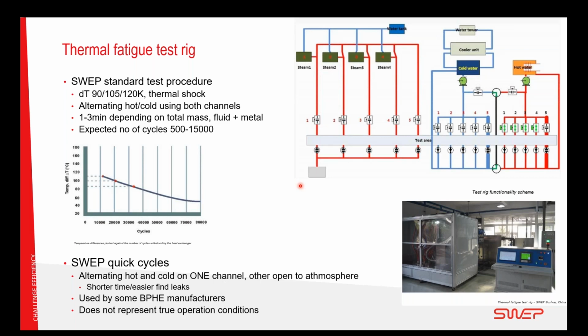And worst case, we will expect somewhere around as low as 500 cycles and then going up to 15,000 cycles. So it's very time-consuming testing, but it has been improving now, the test rig. It's working and we get good reliable data from this one.